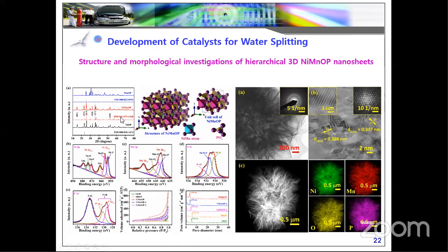So first of all, we go for the structural analysis. Our material fully matches nickel oxyphosphide, because the JCPDS is fully matching. When we dope manganese into the nickel, the highest intensity peak shifts; the 210 peak is shifted towards the higher 2 theta region. You can see the crystalline structure of the nickel manganese oxyphosphide, and this synergistic effect and the metal composition are confirmed by XPS analysis, and the structural properties, especially surface area and pore size, are proved by BET analysis, nitrogen adsorption-desorption analysis.